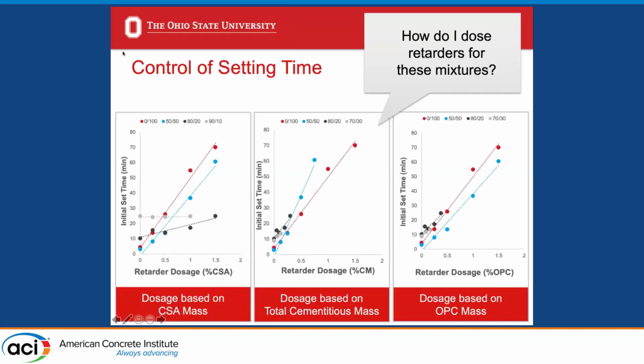Speaking of setting time and retarder dosage, we had struggled a little bit in figuring out how to actually calculate the dosage needed to obtain good setting times for these mixes. We started out, well, let me back up a little bit. You can find in literature the effect of citric acid on OPC cement, and it is a very, very effective retarder. A 0.5% by mass dosage of citric acid in 100% OPC mix results in 160 hours of set time delay. So we were a little bit nervous that if we used more typical retarder dosages in a CSA OPC blend, we would end up with an almost never setting mixture.